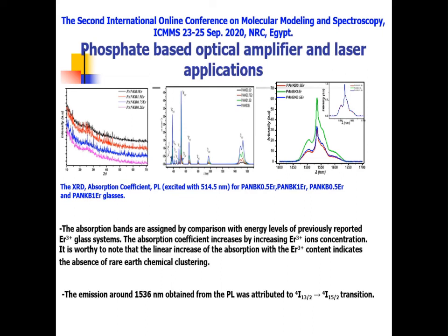The absorption coefficient increases by increasing the erbium ion concentration. It is worthy to note that the linear increase of the absorption with the erbium content indicates the absence of rare earth chemical clustering due to the homogeneity of the host material of phosphate with some doping such as barium and potassium. In the third figure here, we can see the photoluminescence, which succeeded well, and we obtained emission around 1536 nanometer, attributed to the transition from the 4I13/2 to 4I15/2.